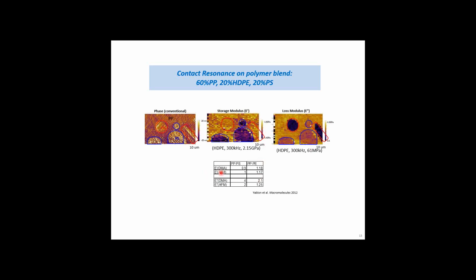Then we can compare the storage modulus measured by the AFM with the bulk DMA, and the loss modulus of the AFM with the bulk DMA. We can see the storage modulus does quite well. The loss modulus struggles a lot more, and part of the reason is that the loss modulus primarily relies on fitting that quality factor, or full width half max, the sharpness of the peak. That's much harder to get right than just the frequency peak position, which is most of the information that goes into the storage modulus.